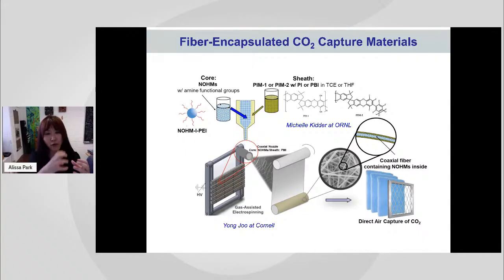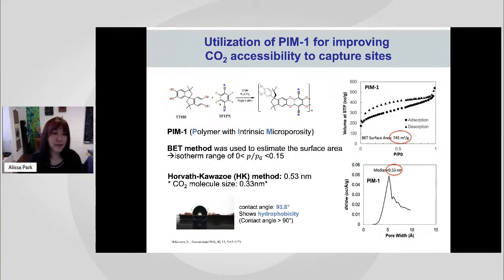By mixing them together and forming them into electrospun fiber, we were able to make the filter system shown at bottom right, like a furnace filter, which has very low pressure drop. One of the reasons we really like the PIM is that this polymer with intrinsic microporosity has a huge surface area, as you can see on the right-hand side, with the right porosity. Another thing we really liked, if you look at the top left, is that there are a lot of fluorine groups on these PIMs, which means that we should have hydrophobicity. If you look at the bottom left figure, this is the contact angle, showing that these fibers and PIMs have hydrophobicity.